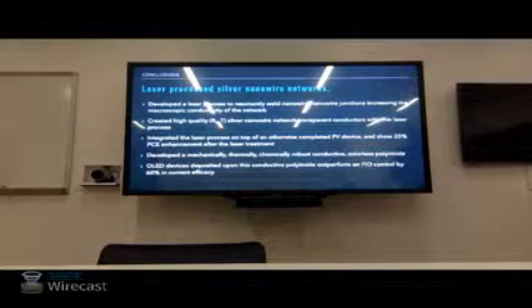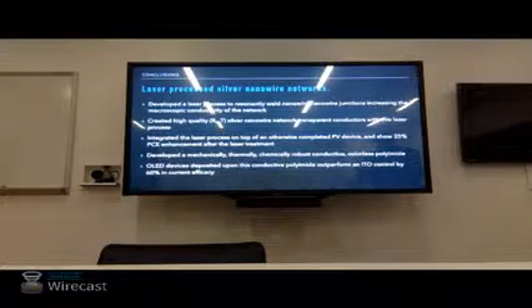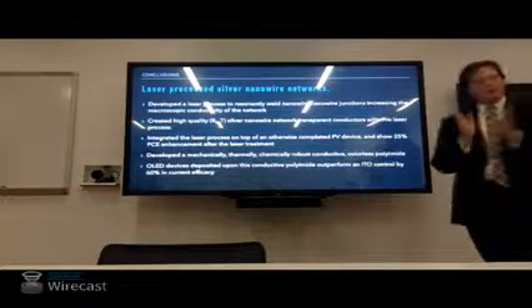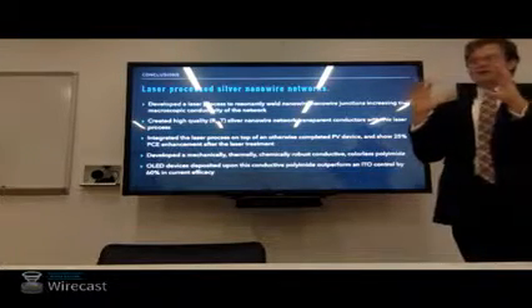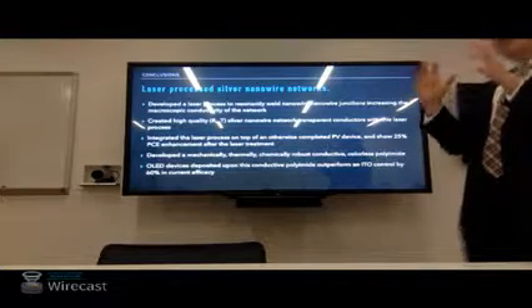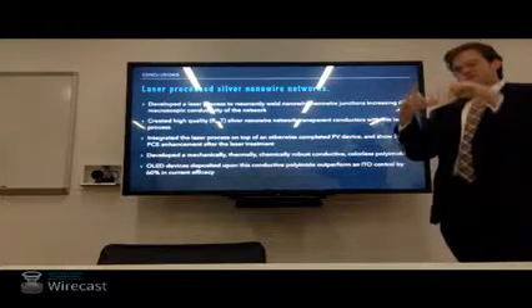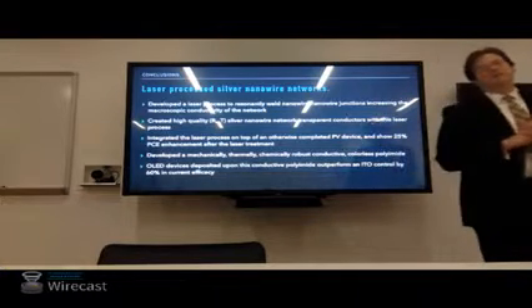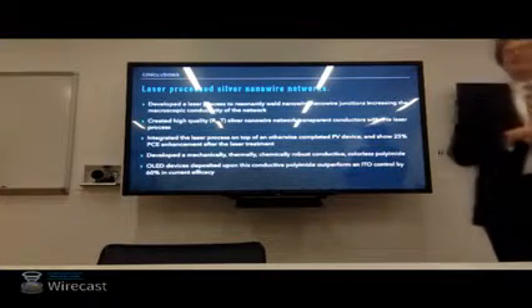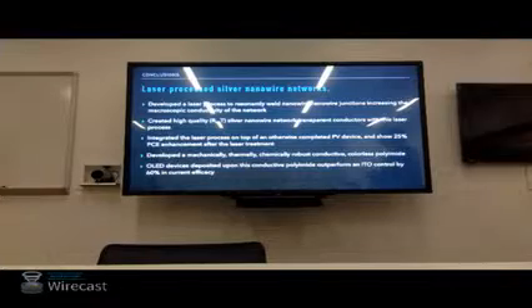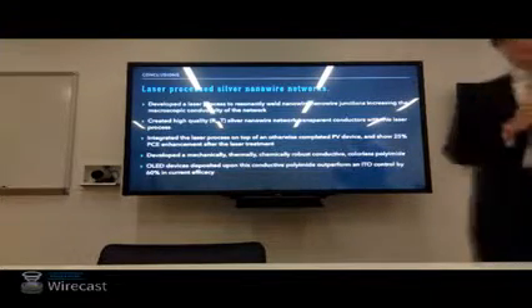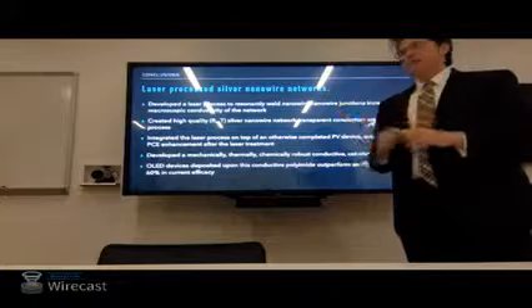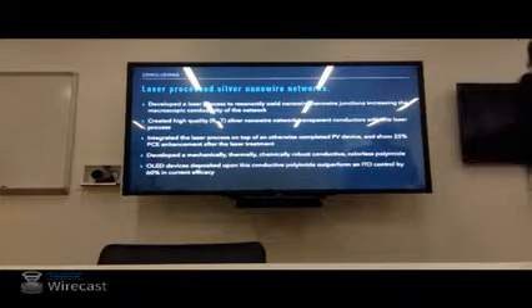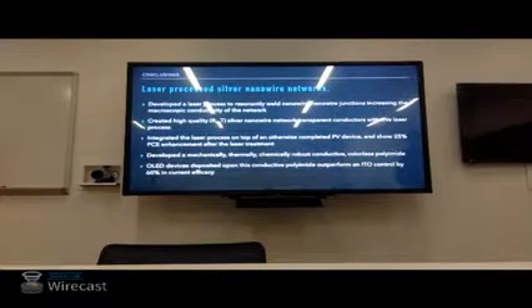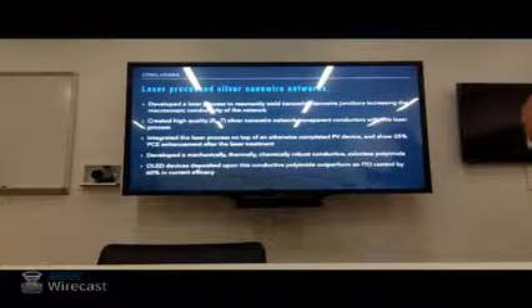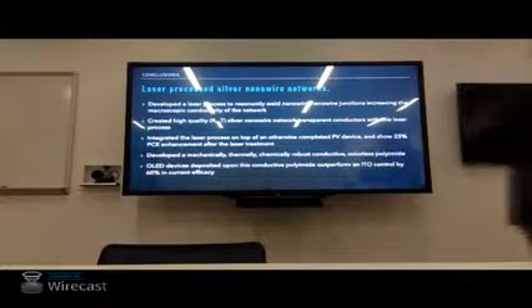Probably what you'd want to do is use a much bigger beam than we use. I didn't really harp on the point, but we use a macroscopic laser beam, and because the energy gets channeled to those junctions, we can use a big beam and raster it along the sample. We're not focusing the laser on the junction. Some people take that away from the talk, but that's not what we're doing. It's a macroscopic beam causing microscopic changes. So maybe what we could do is have a laser that outputs more energy in each pulse, and we can make that beam spot bigger and increase the speed.